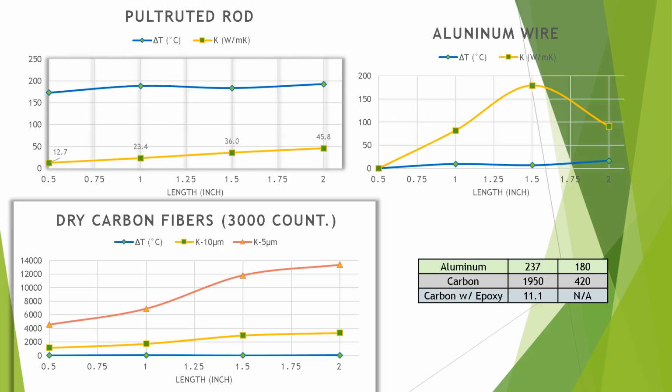Now, we could have a little bit of inflation because when we did the experiment, we didn't have a perfect vacuum. We had only 25 inches of mercury instead of 30 inches of mercury. Our seal between the two compartments could not have been perfect, and we could have had a little airflow and radiation, exaggerating what was happening inside there.